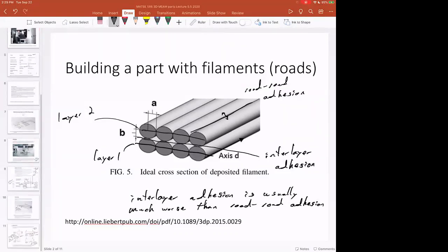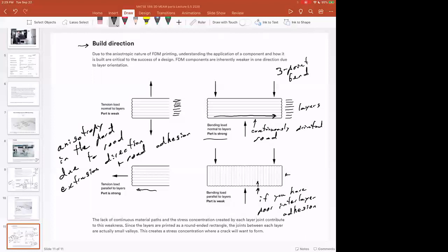So that's just something to think about, and that's what this diagram is trying to point out. These are all interlayer adhesion issues rather than road to road adhesion issues, even though building a three-dimensional part is going to take many roads per layer. That's something to remember, and something you can see as you print parts. If you have really weak interlayer adhesion, sometimes you can break these parts or peel off the layers, or if the temperature of your heated liquefier is too low, the layers don't stick together in the first place. And so you can qualitatively assess this idea of anisotropy and interlayer adhesion. The build direction could make a big difference, especially if you're producing an industrial part.